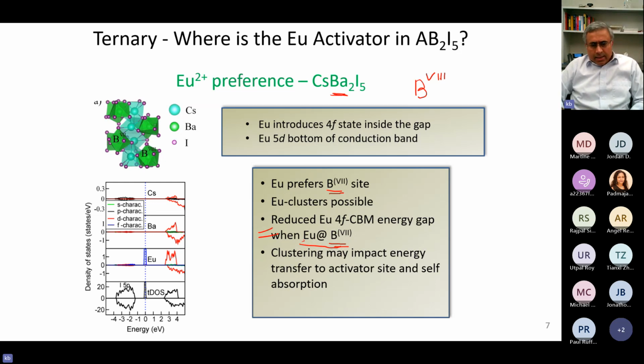And not only that, we also found that in this material, after you dope with europium, the europium starts to cluster, meaning it starts to form small domains where you have some europium-rich region versus europium-poor region, which is obviously not good. You want your activator to be uniformly distributed throughout the crystal. So we found those two things to happen, and that is a little bit of a difficulty, as you don't want them for efficient scintillation. And if you are wondering about this, these are the density of states on this side.